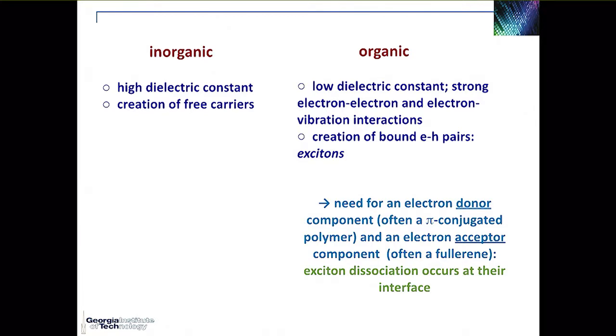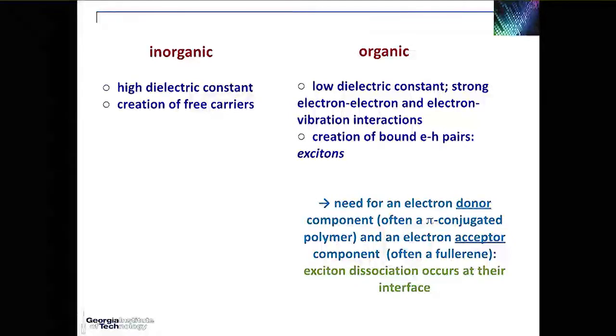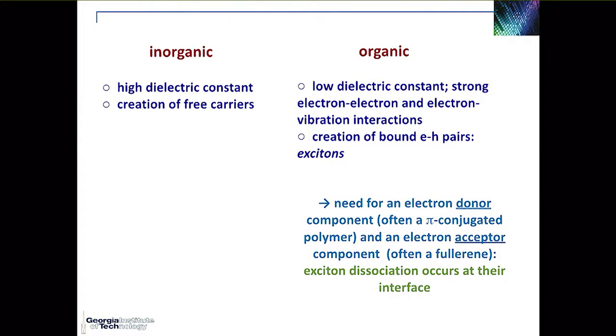This is absolutely not the case for the pi-conjugated organic materials that we are using for organic solar cells. In that case, there are three major components that you need to take into account: not only the lower dielectric constant, but also the very strong electron-electron interactions and electron-vibration, or electron-phonon, interactions that all conspire to bind the electron and the hole as the pi-conjugated material absorbs a photon. And so you form a bound electron-hole pair, that is, you form an exciton.